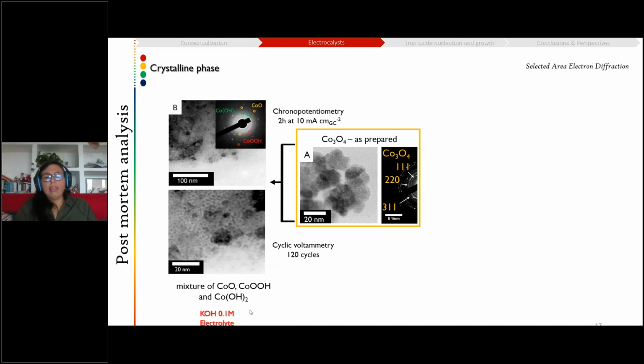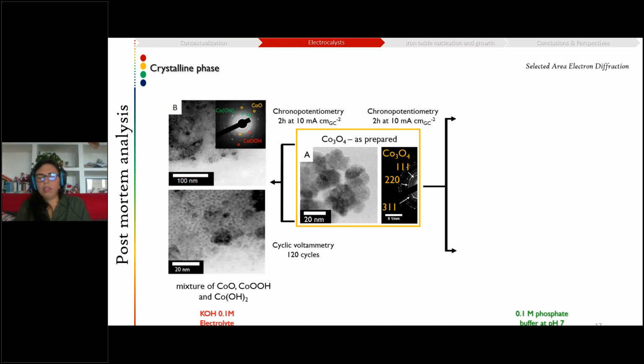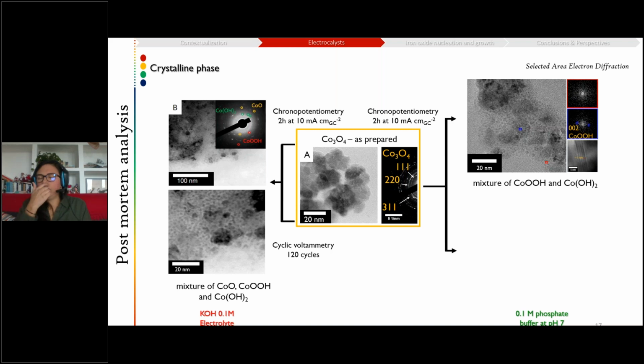Another important thing that we were able to show was that upon cycling, as we mentioned, the crystalline phase changes in a basic electrolyte from cobalt oxide spinel to cobalt monoxide, cobalt hydroxyoxide, and cobalt hydroxide. And we have very small crystallite size, and we have the amorphous matrix, which is not exactly the same as when we use buffered phosphate electrolyte, as we did in this case. So we did the same experiment with these different electrolytes, and we were able to see, again, if we do chronopotentiometry, meaning imposing a certain current to push the reaction, we will find again small crystallites, and we could even find the layered structure of cobalt hydroxide.